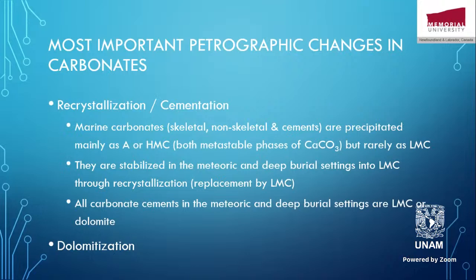to low-magnesium calcite during meteoric diagenesis and also in deep burial settings when the sediments are taken to deep burial. And this happens through recrystallization and water-rock interaction. All the aragonite and high-magnesium calcite, the metastable phases, are replaced by the normal low-magnesium calcite, LMC, we call it like an abbreviation. And this is the stable phase of carbonate.